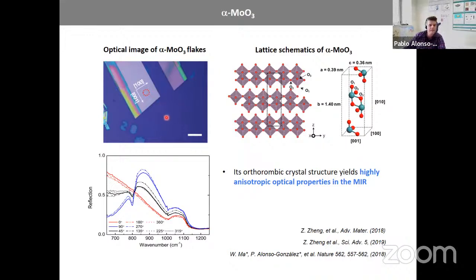When measuring the optical properties in the far field, in the long infrared range, you can see that it reflects quite a lot in some bands. It reflects because, in particular, epsilon is negative in these bands. This is the Reststrahlen band. So here we believed at the time that it could support phonon polaritons in these regions. But these polaritons would be expected to be really anisotropic because of the intrinsic anisotropic nature of the material.